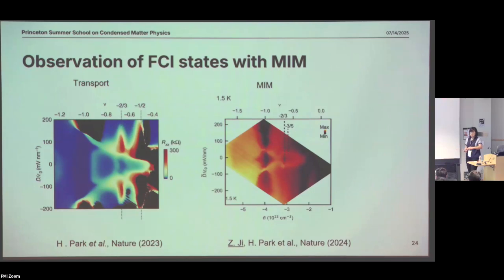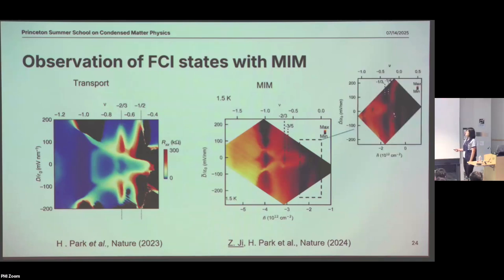So effectively, you can see that this microwave probe, when the tip is sitting inside the bulk, acts as a local conductivity measurement. And what's more, our microwave probe is actually very sensitive to pretty insulating materials. For example, in DC transport measurement, when the filling factor is very low, very close to the charge neutrality, because twisted MoTe2 is a semiconductor, the contact resistance becomes super large. And when the contact resistance is large, you will see something like this black region, which cannot be very well resolved. But in the case of microwave measurement, you don't have that concern. You are capacitively coupled to the material.